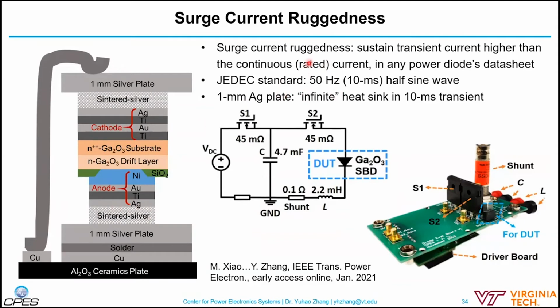And also, it is the ruggedness that is designed in the power devices, including any power diodes data sheet. So we build up this surge current circuit according to the JEDEC standard, and we test our packaged devices in this circuit. In this roughly 10 millisecond transient, we put a 1 millimeter thick silver plate on both sides, and within this transient, this 1 millimeter silver plate will act as an infinite heat sink.